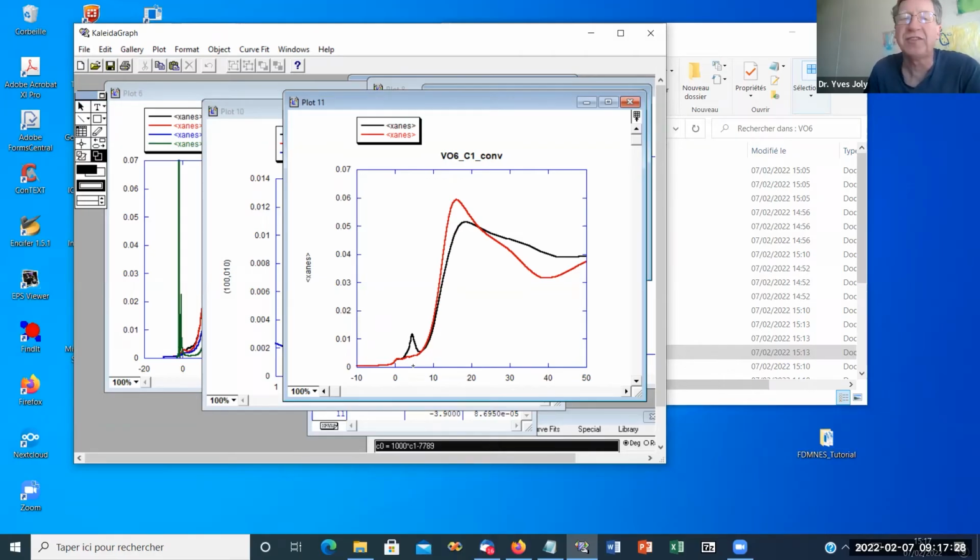But if you were, for example, at the zinc edge, which is 3D10, if you have not the center of symmetry, the hybridization occurs, but it's in occupied states, so you don't see a pre-edge at the zinc edge. But for all the other edges, if it's not 3D10, copper sometimes can be 3D10, you have a pre-edge if you have not the center of symmetry. Okay, so even if it's small, the pre-edge is very important to check because there are many interesting details.